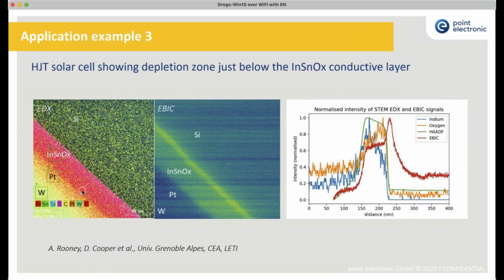And then a third example, and this is illustrating another strength of doing EBIC in the TEM, is that you can do other kinds of analytical techniques at the same time. So before we looked at structure, now we're looking at composition. So from the same sample, on the same location, we're recording EDX and EBIC. And EDX is giving us the composition, and this is a heterojunction solar cell. And we have a silicon-to-InSnOx heterojunction somewhere in this region. And we can pick up with EDX the composition, and we can see the layers. And the question was, where is the junction? Do we have a junction? Where is it? What does it look like? And it's very straightforward. You just do one image, and you have a location of the field, and you can start to do more analysis from it.